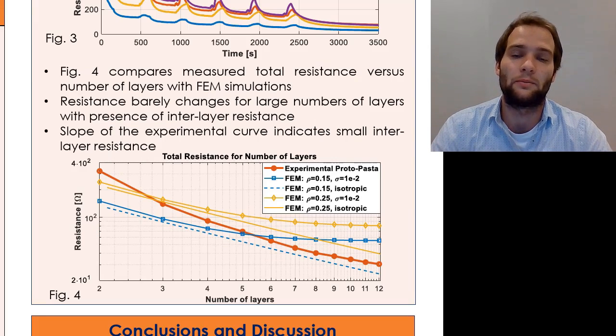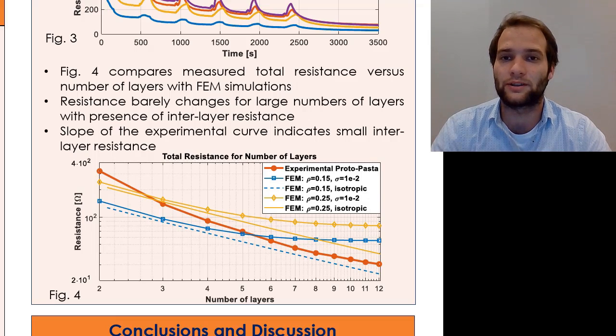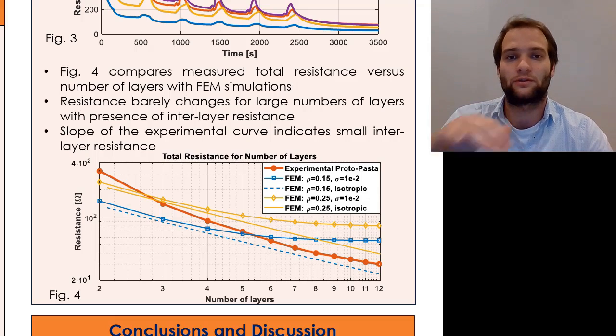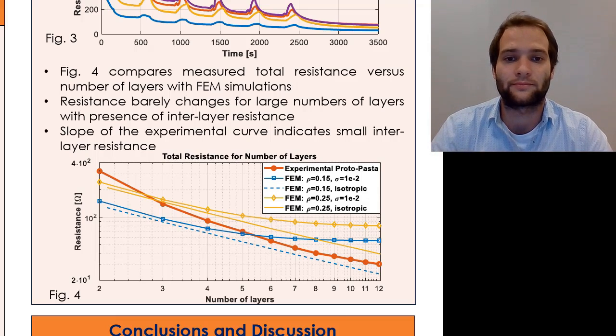Furthermore, if we compare the measured resistance per number of layers to the finite element method simulation, we can see that added layers for a large number of layers with the interlayer resistance don't make a big difference. However, for samples without an interlayer resistance, adding layers keeps on lowering the resistance significantly.